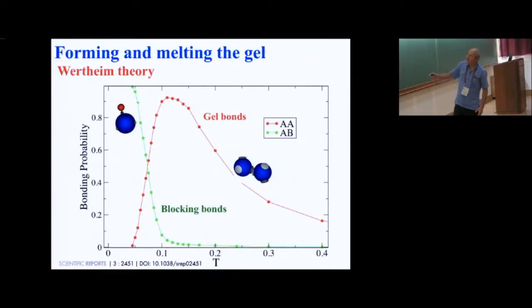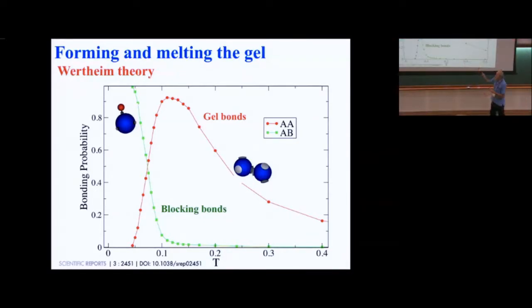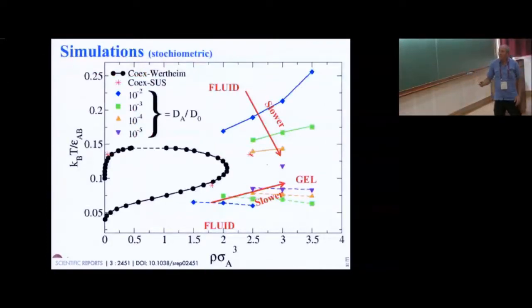So on the computer I do it, and when I solve the equations, in this case again Wertheim theory, I get that the blue-blue bonds now reach 90%, and then they go down to 0 when the red-blue bonds start to become very intense. The number of blue bonds goes to 1. So this seems to be the right ratio parameter that we have picked. So we can do simulation for this ratio parameter and see if these theoretical predictions are verified.